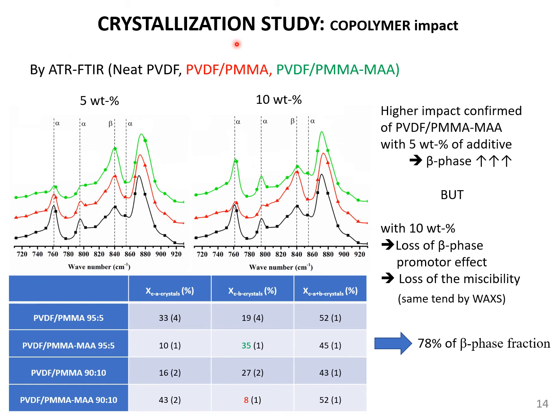To understand the crystallization behavior that we obtain by fast DSC, we investigate by infrared the copolymer impact, particularly in the case of neat PVDF as a reference versus PVDF containing PMMA and PMMA containing methacrylic acid.